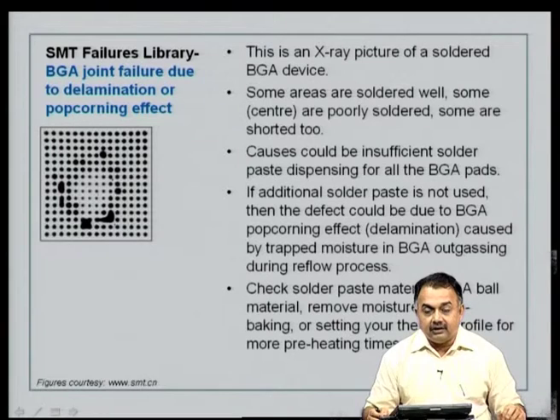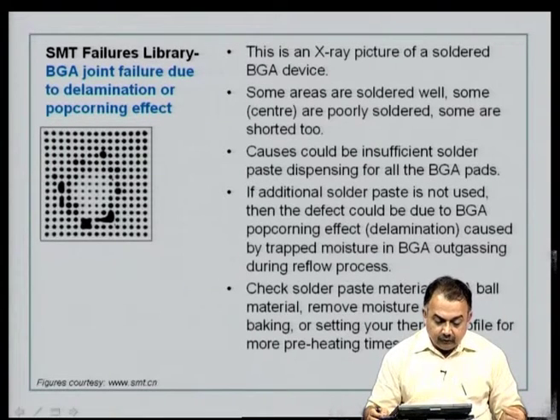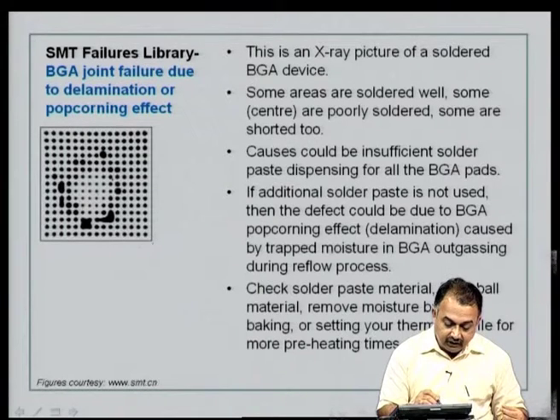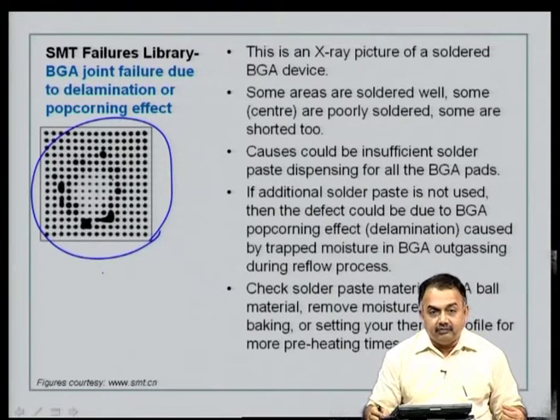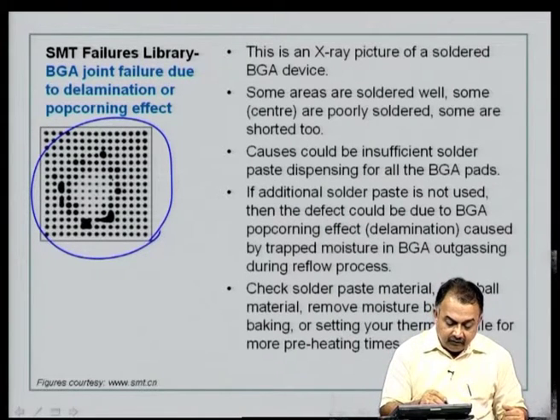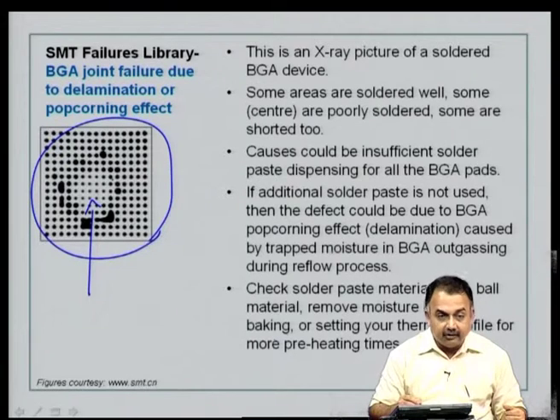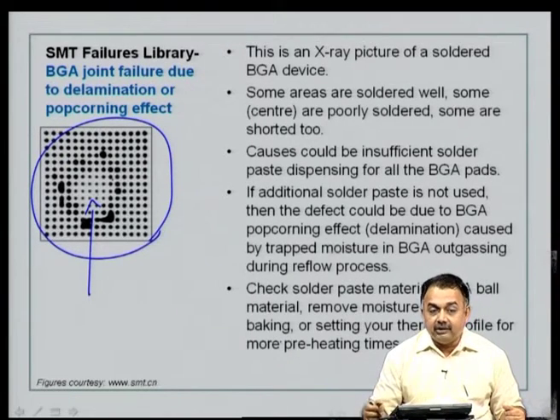Because BGA is being used in large numbers today, failures are bound to happen during assembly of BGAs. So, look for failures, especially the popcorning effect or the delamination, and also because the die attachment of the BGA, the solder ball attachment cannot be viewed by the normal microscopes. You have to use X-ray micrograph and see whether there is a die crack or a popcorning effect, or simply important issues like unequal solder paste dispensing, creating, for example, the areas that you see here in the middle, where you are not sure whether it is a wet joint or a reliable joint because of low solder volume, that has solder paste volume that has been dispensed.